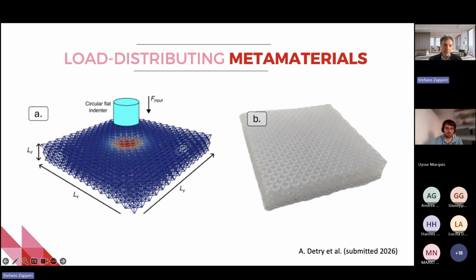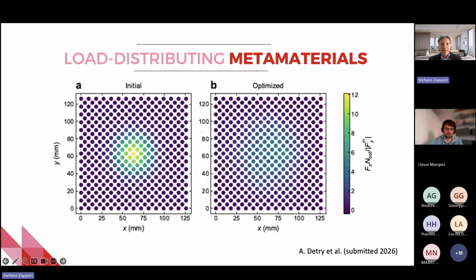And here is the structure that we simulate, and then we can also realize it by 3D printing. And this paper is currently submitted. And Andrea De Tri is the person who did all the experiments. And I have to mention all these last simulations were done by Hannes Holai. So here are simulations, and you see that in the initial structure, you get very concentrated load. In the optimized, this is the bottom plate, you get a much broader spread of the forces.